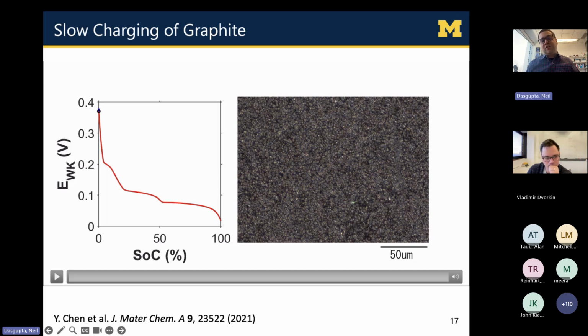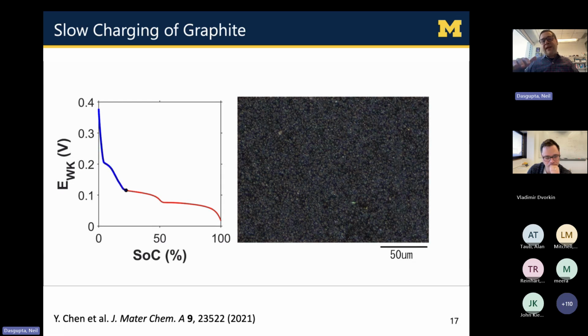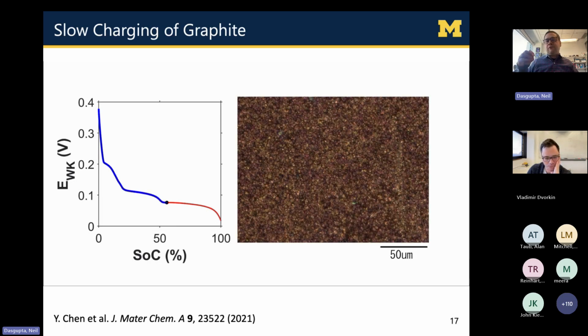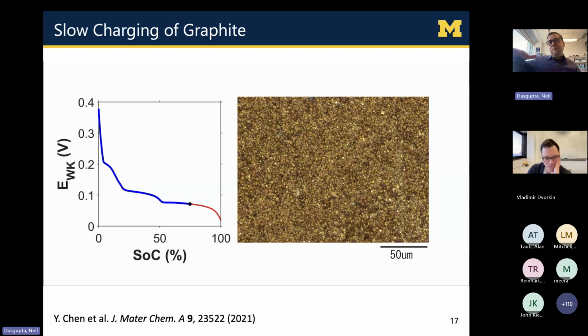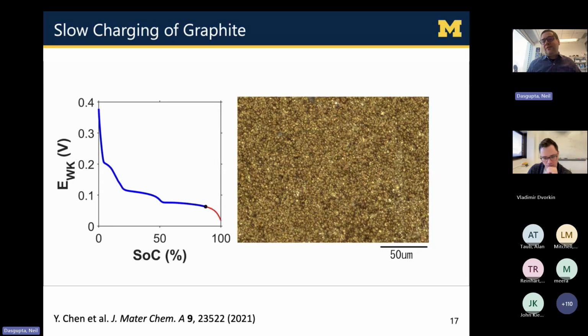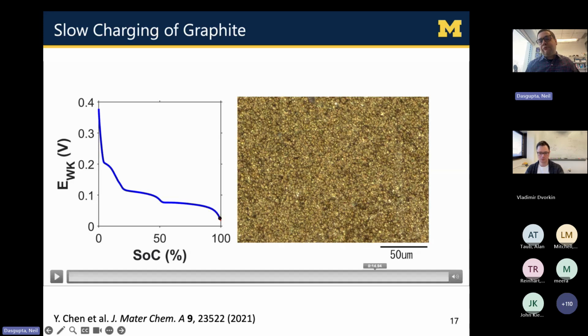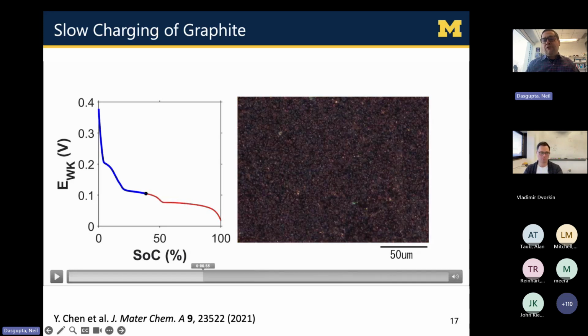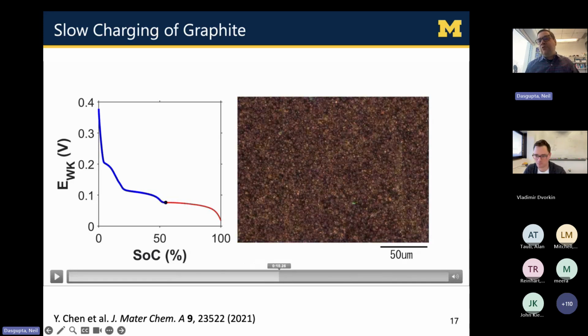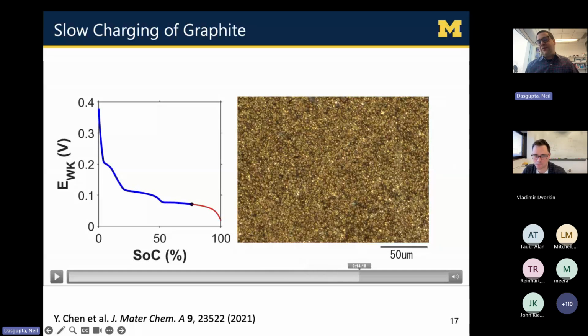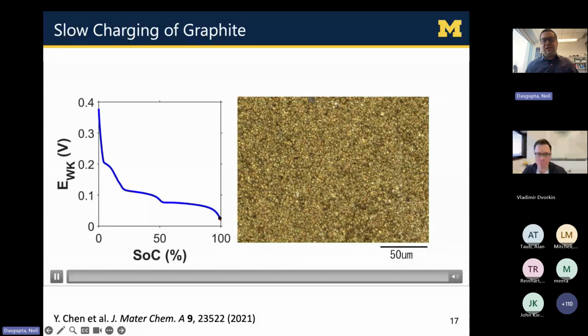And when we slow charge the graphite, when we don't do this at a fast rate, I'll start to play the video, we can see that we're able to measure the voltage of the graphite anode as a function of state of charge, and we see the color starting to change on the right-hand side. Again, those particles are changing from gray to blue to black to gold. Now that we've eliminated that in-plane gradient, you see all of the particles basically change color at approximately the same time. So if I move back and forth, you can see we have a very uniform lithiation of the graphite electrode under this slow charging condition.